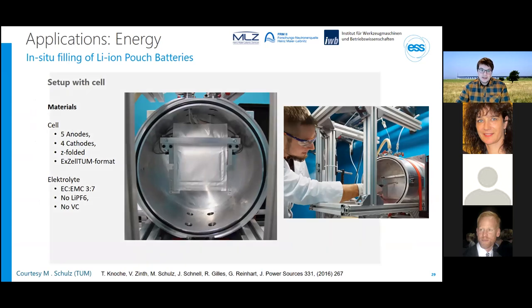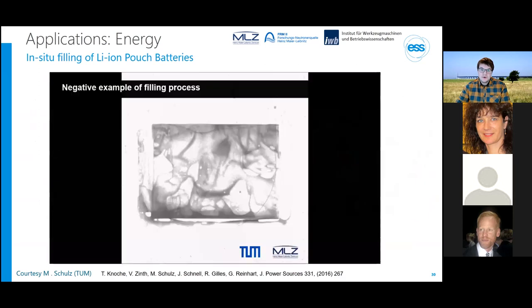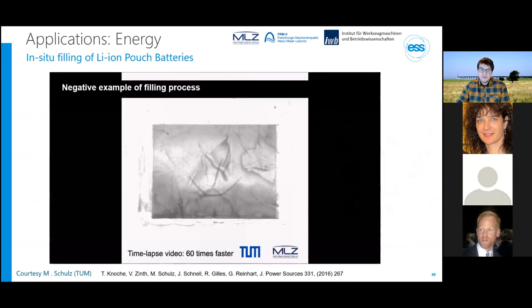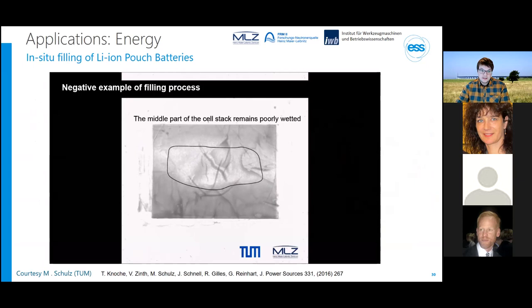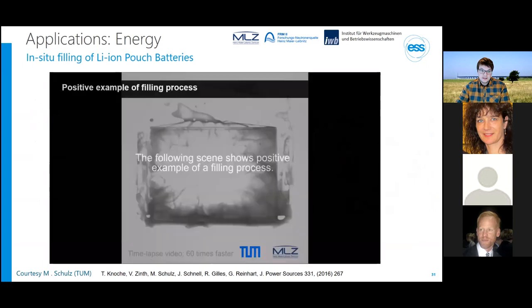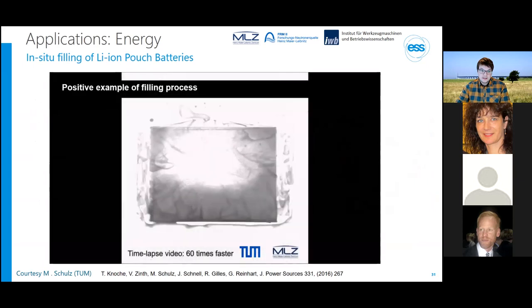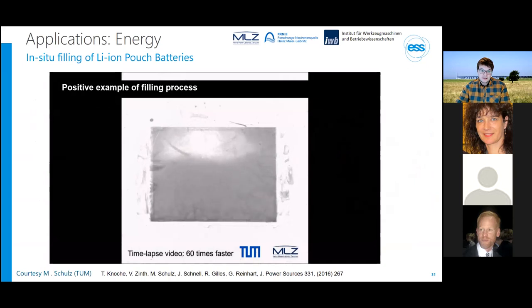And this is then an example of a non-ideal filling process where the middle of the cell actually remained unwetted. And in contrast, you can see here a good example of a filling process. The study allowed them to gain insight into the influence of the process parameters so that the production process could be optimized, leading overall to a more stable cell performance and cost reduction due to the faster processes and lower scrap rates in the manufacturing process.